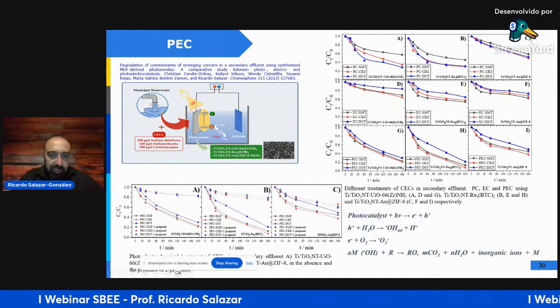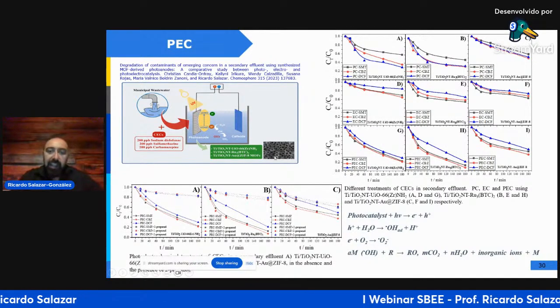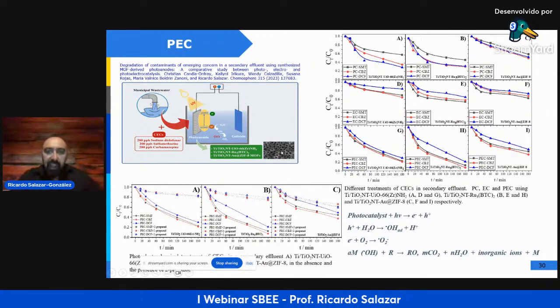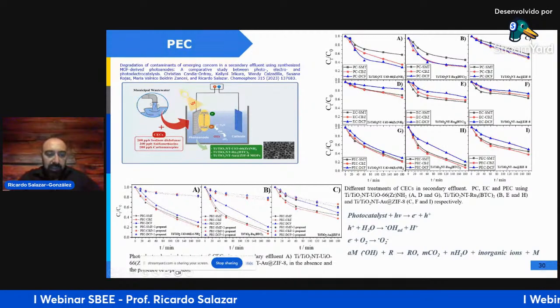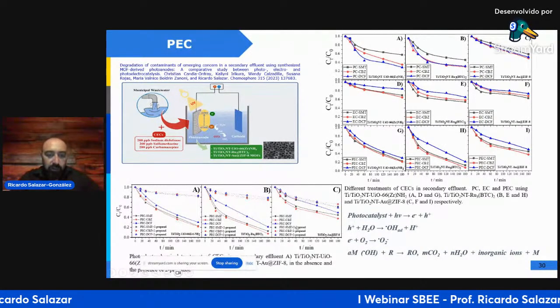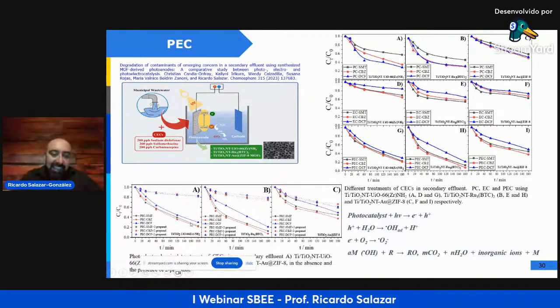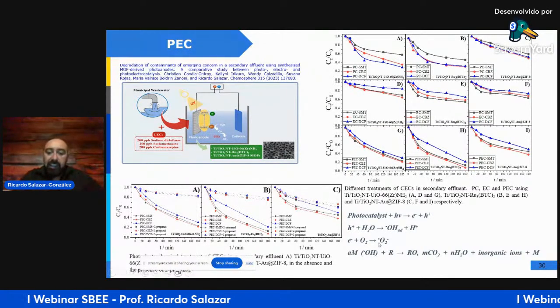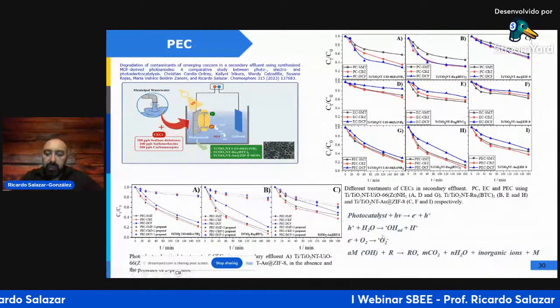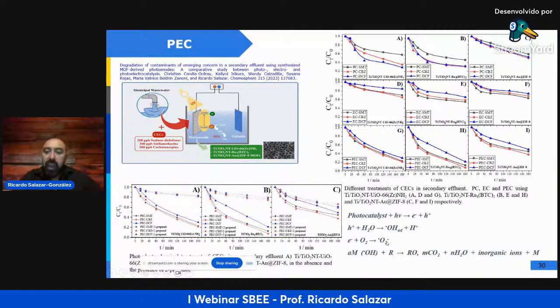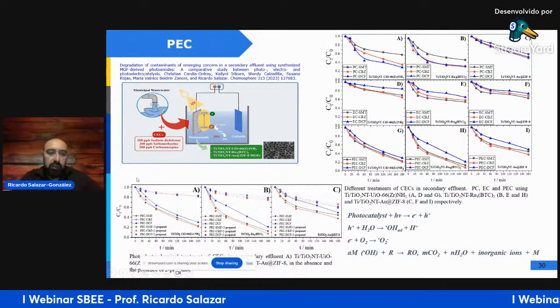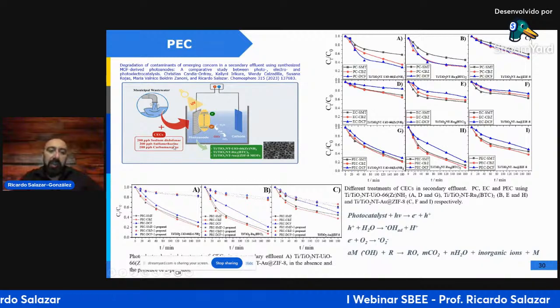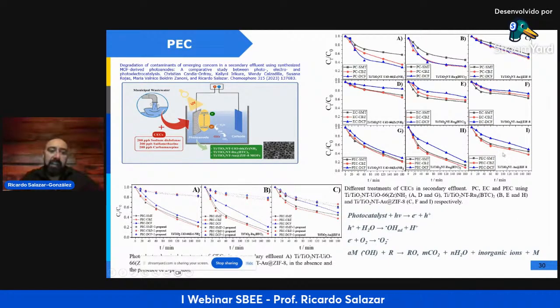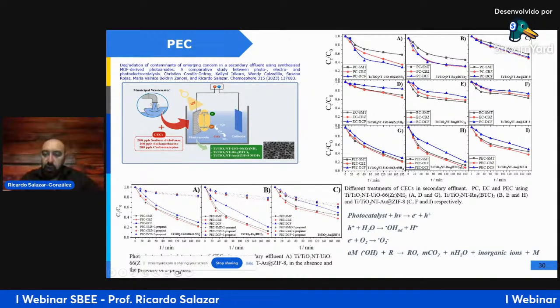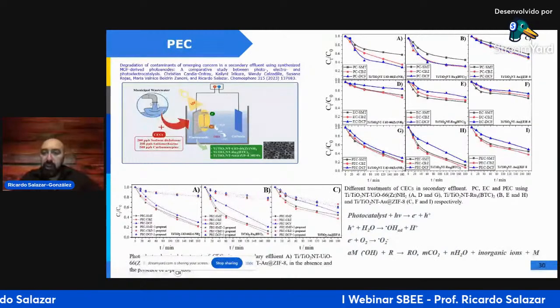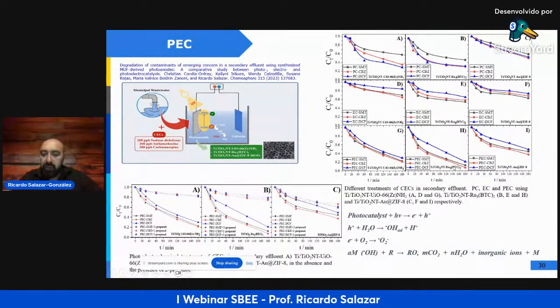Here, the photocatalysts have a nanotube structure, and we demonstrate that with the different photoanodes, we produced hydroxyl radicals and superoxide anion. Both the hydroxyl radical and superoxide react with the contaminants of emerging concern. We studied the elimination of diclofenac, sulfamethoxazole, and carbamazepine. And only by photoelectrocatalysis, we obtained the complete elimination of the mixture of pollutants in the real wastewater.